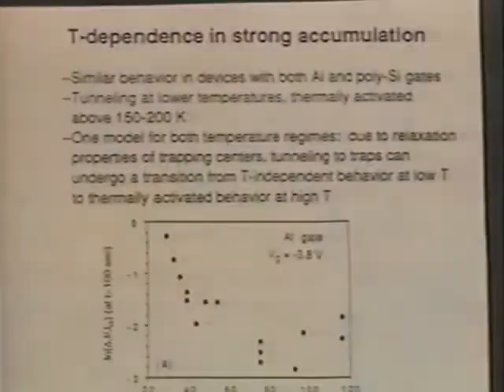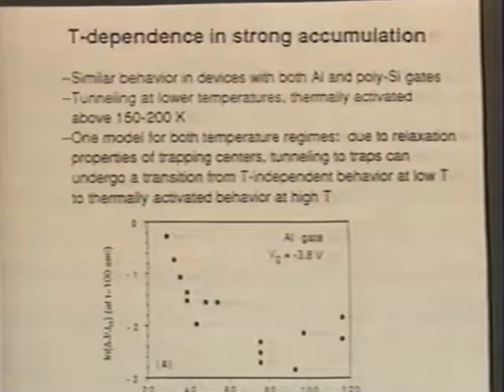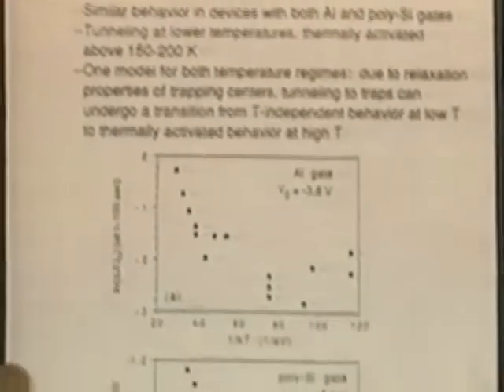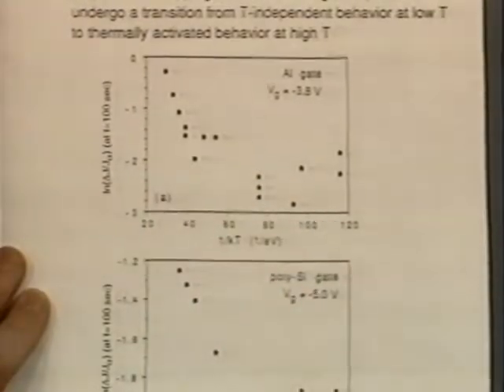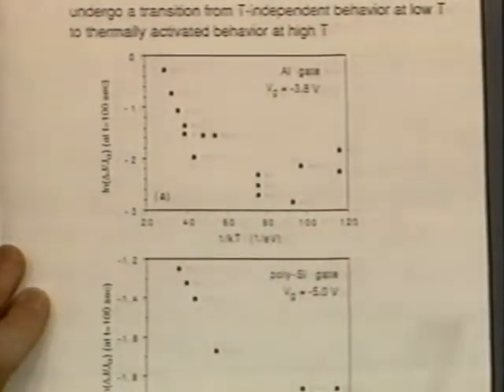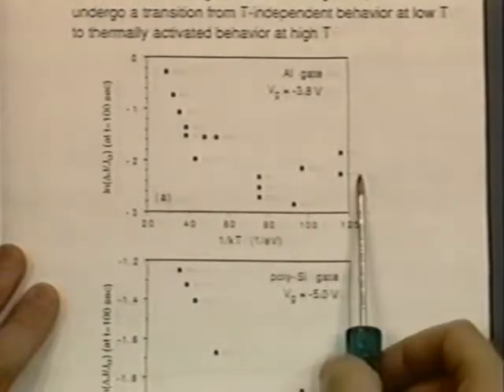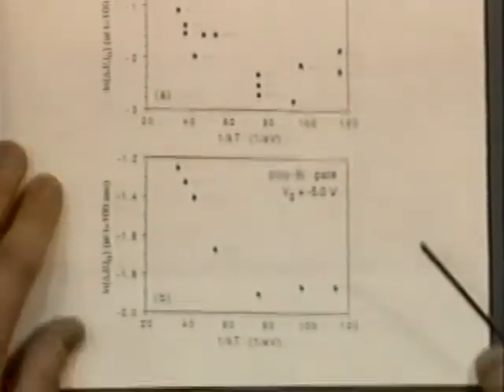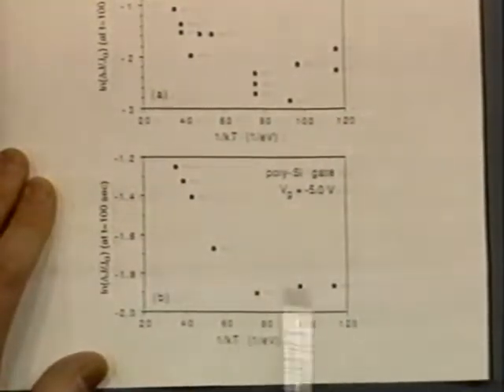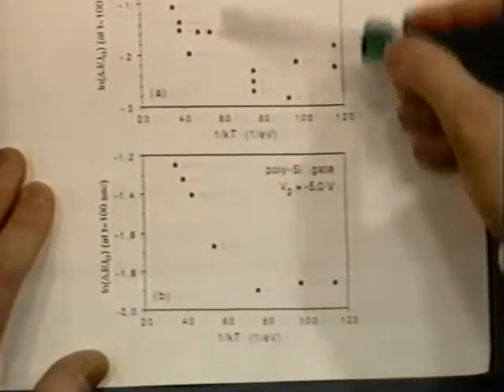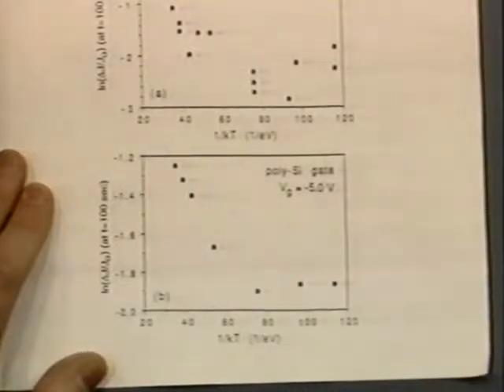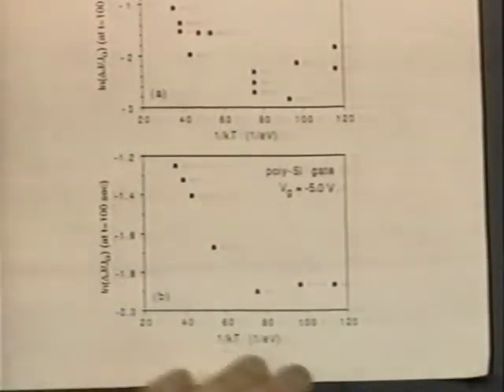Let's look at the temperature dependence. Again, this is for injection from the gate. I'll just go to the graphs. Here we have log of the fractional change in current versus 1 over kT, an Arrhenius plot. At low temperatures, it's kind of flat, kind of noisy for aluminum gate devices, and exponential increase at high temperatures. And for polycrystalline silicon gate devices, kind of temperature independent at low temperatures, exponential at high temperatures. And it's about 150 degrees Kelvin is where there's some turn on of this thermal activation.